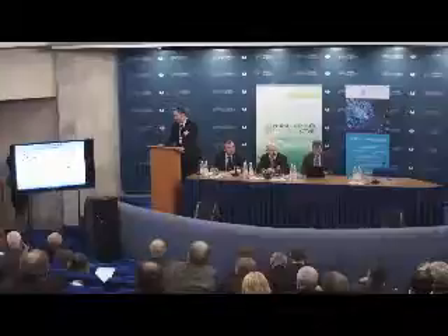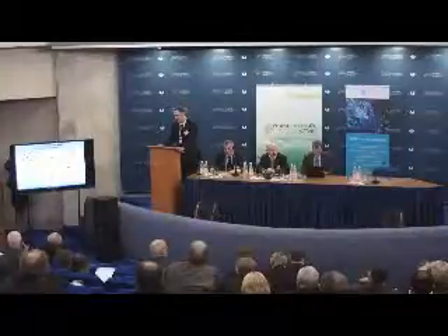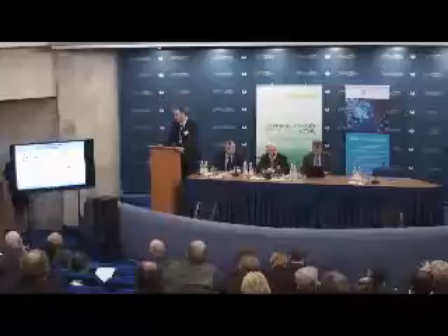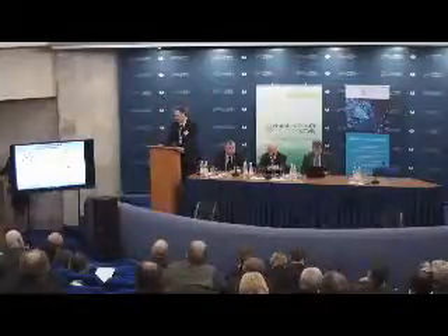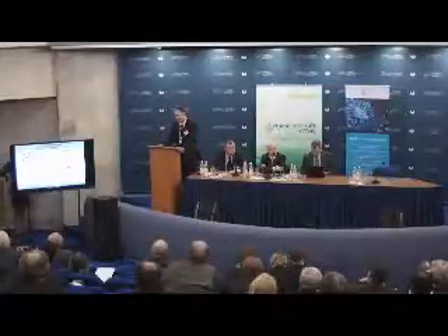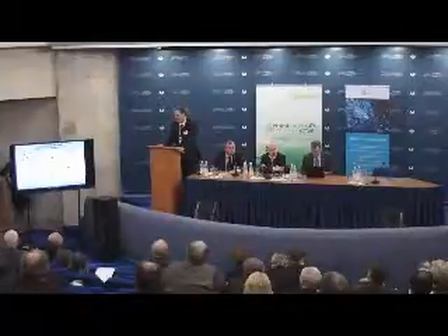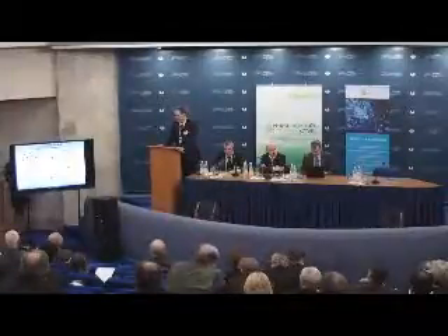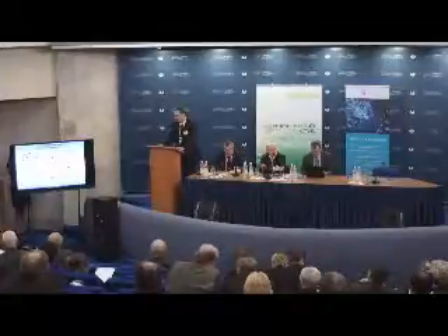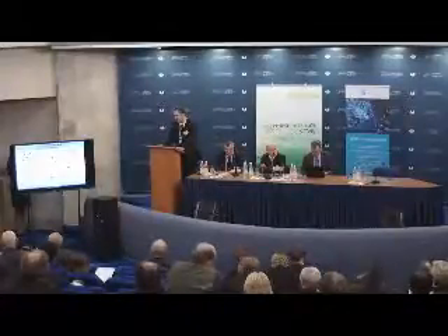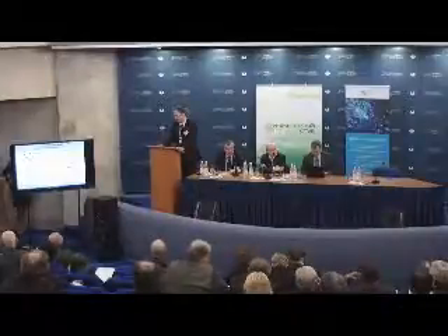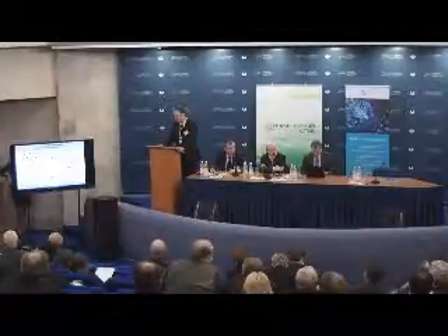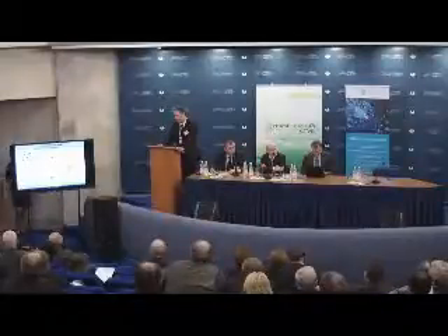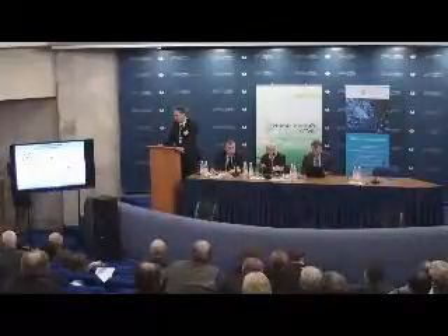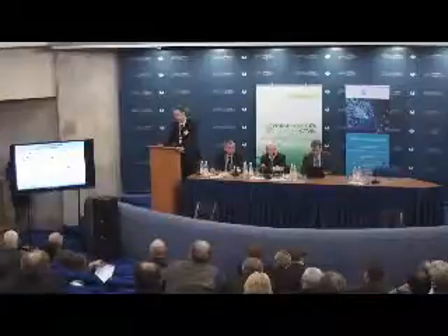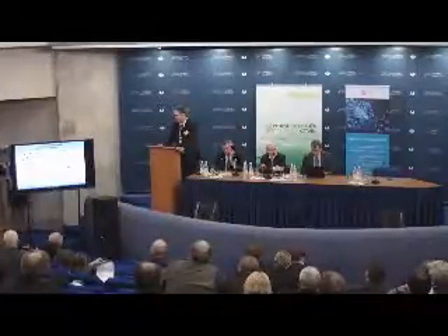And by repeating this cycle we can grow films bottom up like piling Lego bricks, so that we can make a digitally controlled process and on all three-dimensional surfaces, also in nanoscale, like nanometer scale trenches and vias and microcracks and nanowires and nanotubes inside nanopores, but also on macroscopic objects, because these gases, they see all the surfaces and react on all the surfaces.